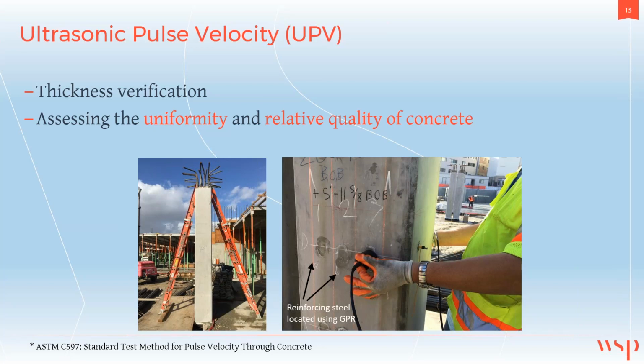Ultrasonic pulse velocity uses similar principles, but is often employed in what you might refer to as a pitch and catch mode, where you have a transducer at two surfaces of an element and you induce a signal of known frequency from one element and it's received at the other. It's particularly useful in assessing uniformity of the element, quality of concrete, for example, because of the wave velocity through the concrete, which can be affected by changes in its quality.